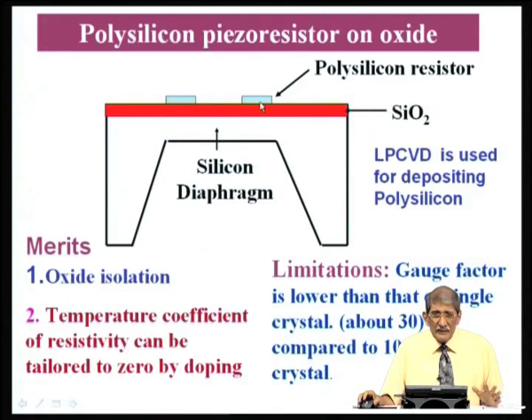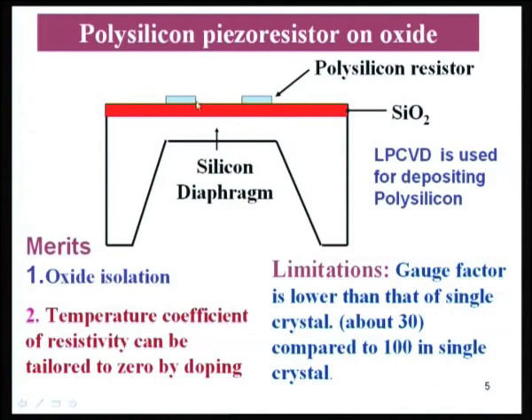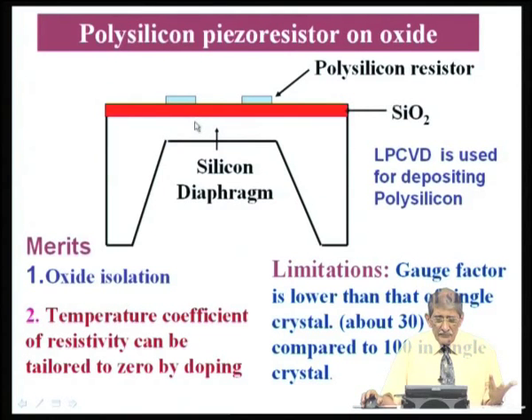I have shown 2 of them, there will be 4 actually. So, I have shown 2. So, these 2 resistors are there. You can see there is no connection between this resistor and this resistor, unless you make a deliberate connection outside. So, if I take this resistor, between these two there is oxide. So, the resistivity between these two layers is 10 to the power 14 ohm centimeter, which is insulating layer. So, you get oxide isolation between the two resistors, which will stay in isolation even if you go to temperature like 500 to 600 degrees centigrade.